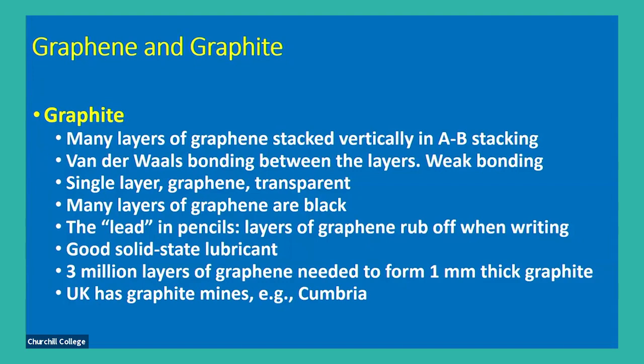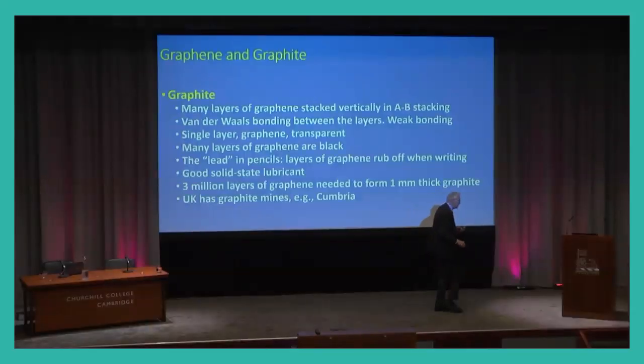A single layer of graphene is transparent. It's in fact 97% transparent, almost as transparent as glass. Many layers are black, and that's because a single layer is 97% transparent, so it's 3% absorbing of light. So if you get many layers, each layer is 3% absorbing, and then it's black. And the lead in pencil, and over here I have a rather large pencil for a demonstration.